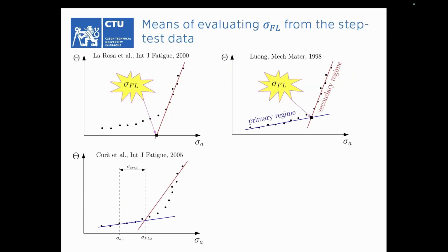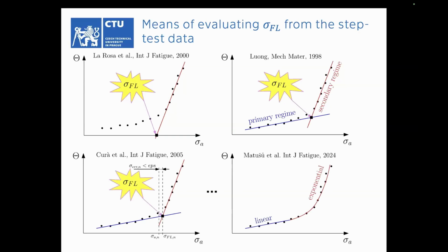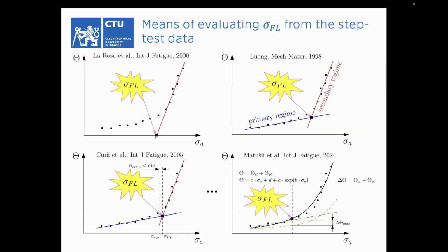There are several methods to evaluate the fatigue limit from self-heating data. The La Rosa-Risitano method is a conservative one, using two linear fits. Since these methods don't say how many points you should use to fit one or another line, some more rigorous approaches have been developed. My colleagues found that this data is usually well fitted with a coupled linear and exponential function, and they postulate that the fatigue limit lies at the point where the difference of the linear and exponential part has its maximum.